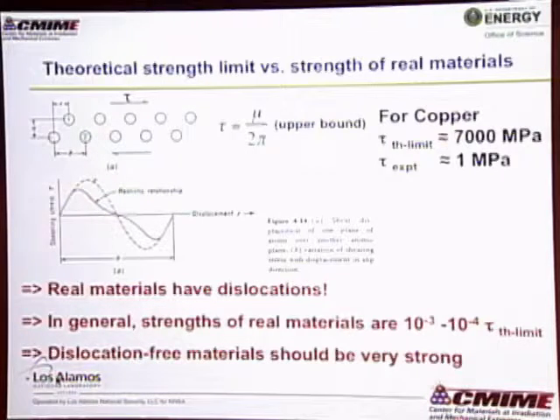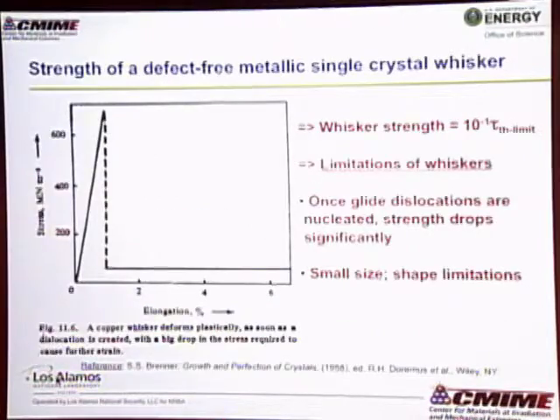In reality, it's 7,000 times weaker. So the question is, well, why? Well, real materials have these defects known as dislocations, which ends up lowering the real strength of materials. But you can form a hypothesis. All right, well, if this is the case, a dislocation-free material should be very strong. And indeed, you can test that.